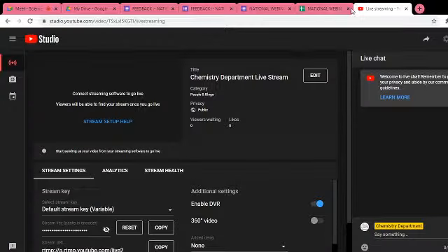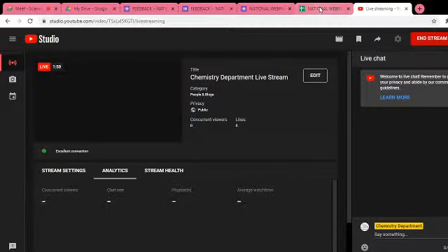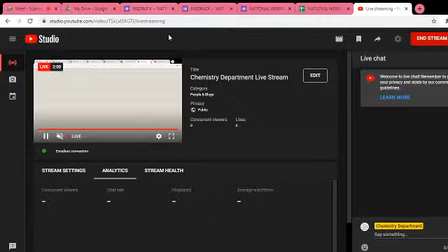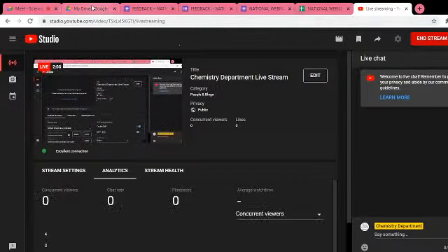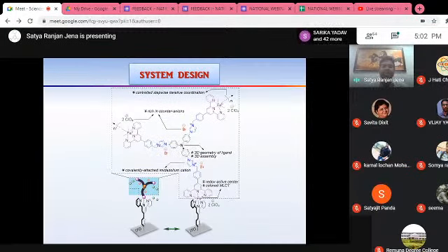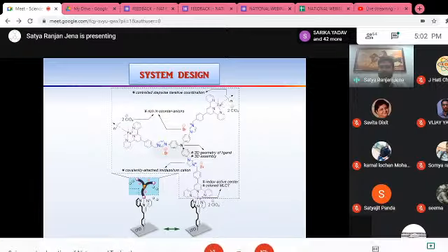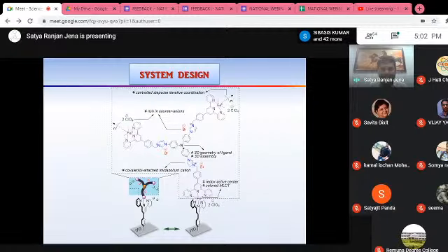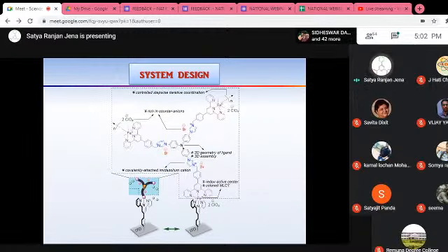Then the iron terpyridine moiety that is used gives a metal to ligand charge transfer transition at 570 nanometer, which is hugely colored. When you oxidize it, that means when you convert iron 2 to 3, that charge transfer is prohibited, because your metal is already electron deficient, so it will no more give the electron to the ligand antibonding orbital. So you will see it colorless. In that way, the previous examples we saw, that mechanism is actually going on.